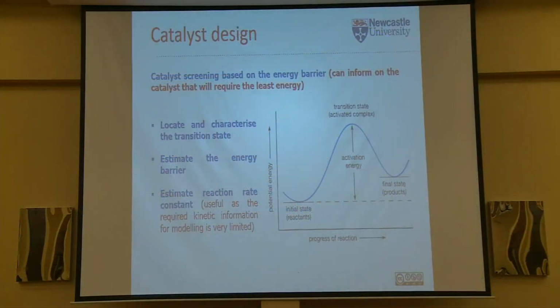a good part of our research, as I've mentioned, part of the things that we do is using computational methods to design catalysts. And we've used some of this application to develop a simple methodology that we can be using to assess different catalysts. Now, this simple methodology, what we do is to simply estimate the energy barrier, because for a start, a key criterion for assessing catalyst suitability for us is the energy barrier associated with the catalyst in ammonia cracking.